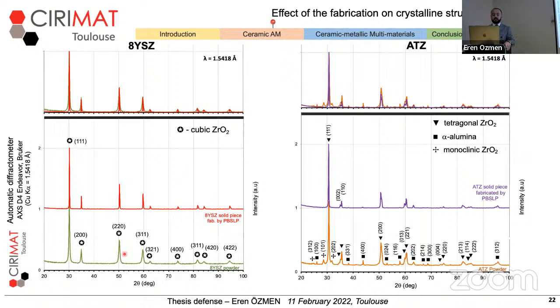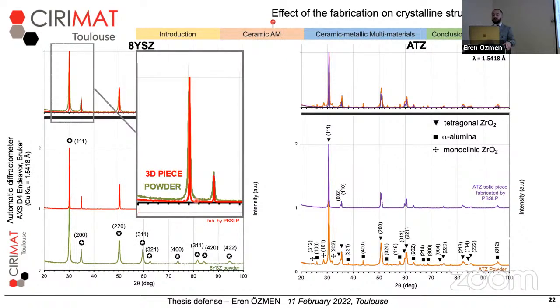When we stack these patterns on each other, we see that there is a narrowing of the peaks for the fabricated pattern. And when we calculate the crystallite size with the Scherrer equation, this narrowing was an indication of crystallite growth. And we see that after calculation as well.